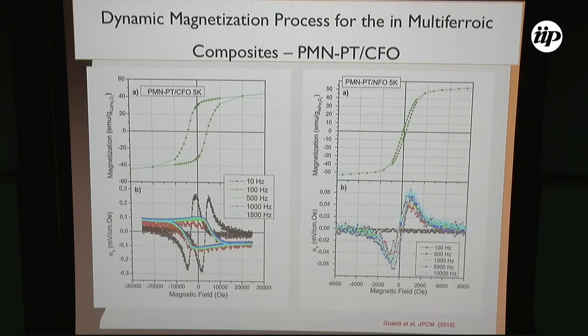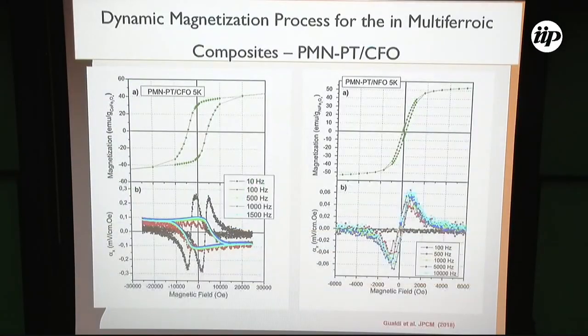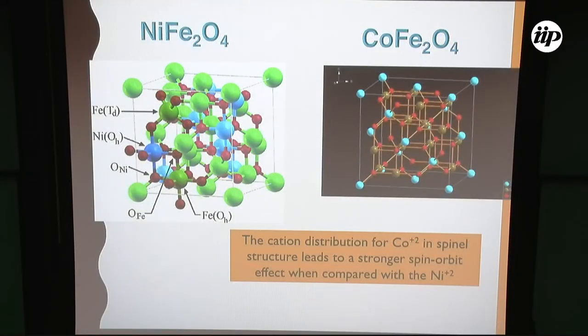What is the difference between nickel ferrite and cobalt ferrite? The difference is associated with the spin-orbit coupling. Nickel ferrite and cobalt ferrite are both in a spinel structure, but cobalt ferrite has a strong spin-orbit coupling due to cobalt, and the nickel ferrite does not exhibit the same behavior.